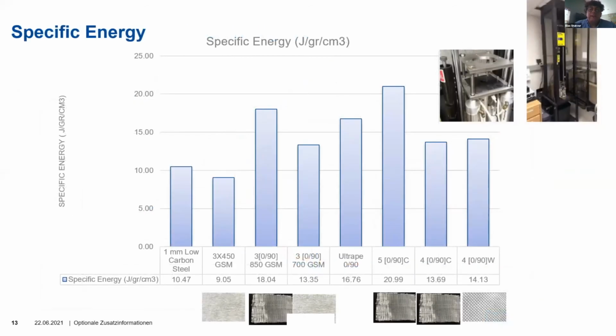We did different DOE studies, and we looked into what kind of a glass fiber it needed for different impact by making specific energy to increase the specific energy, increase the impact energy absorption, but yet to compare it to the carbon steel that it is as the control. And you can see from this graph, like, 5 layers, 4 layers of 0-90 can really be a good fit to replace steel as well.